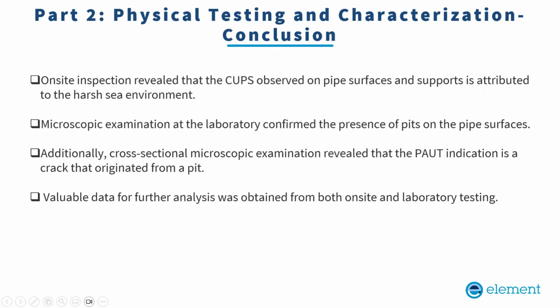So in conclusion, for part 2 of the analysis, we can say that on the cups observed on the pipe surface, microscopic examination at the lab confirmed the presence of pitting, and there was also observation of chlorine on the surface in the lab-based observation, which confirmed our observation or speculation. We also did microscopic examination and saw that there is a through-thickness crack which originated due to pitting.